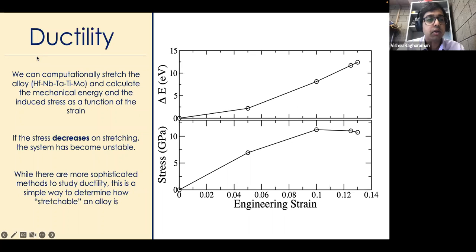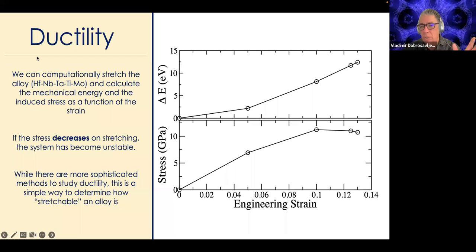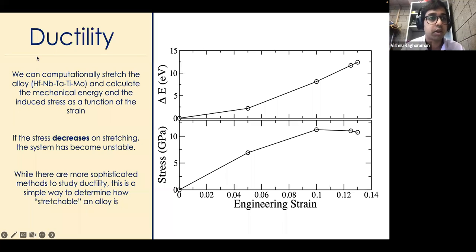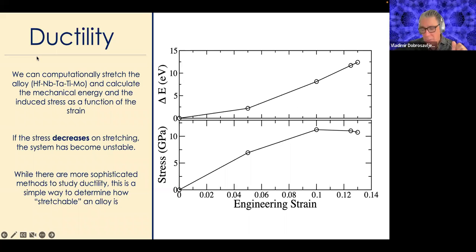I've noticed that at low strains, I've relaxed quite a bit of 5 and 6 element high entropy alloys, and they don't take much time to relax. But at higher strains, it becomes really difficult. So at almost 15% strain, I just could not relax a 6 element high entropy alloy in practical time. So is this compression or it's stretching? Is this compression? No, stretching. Stretching. So you're saying when you actually stretch it, it has a harder time relaxing?